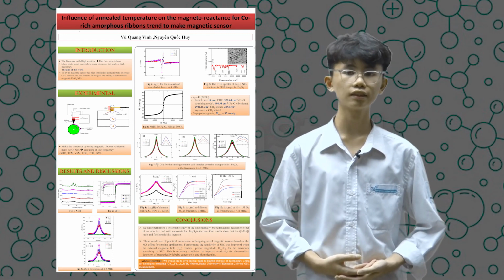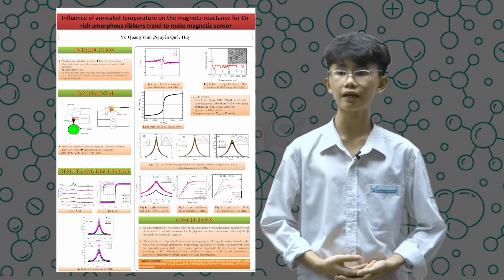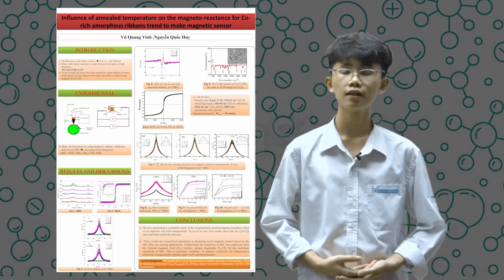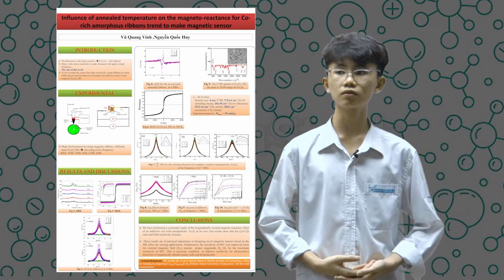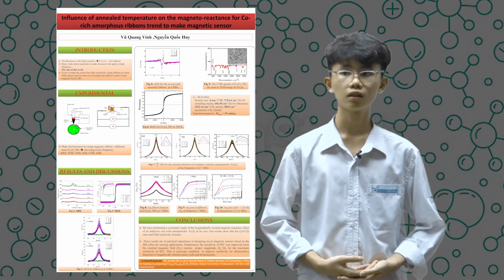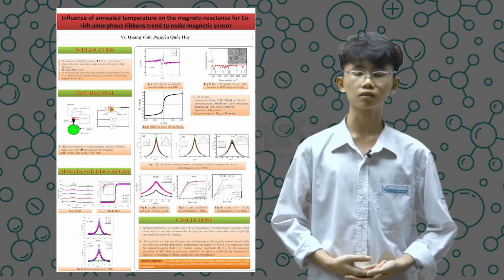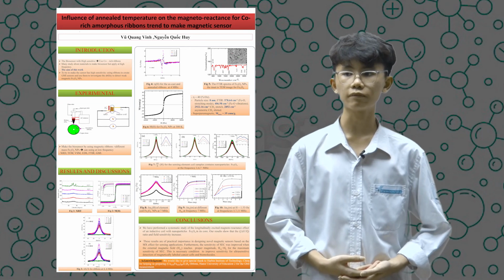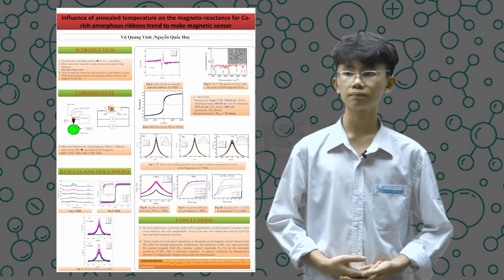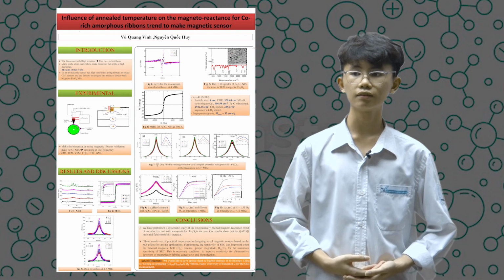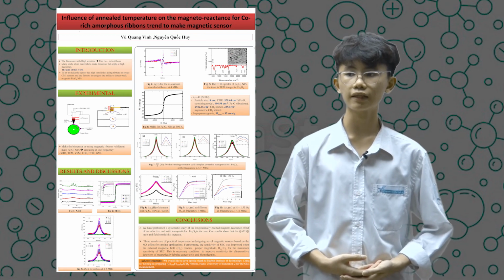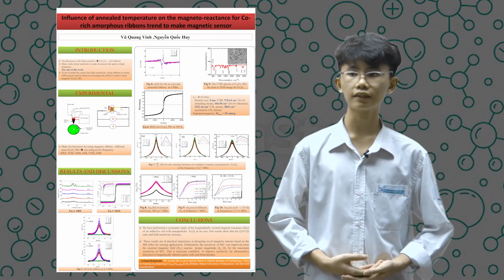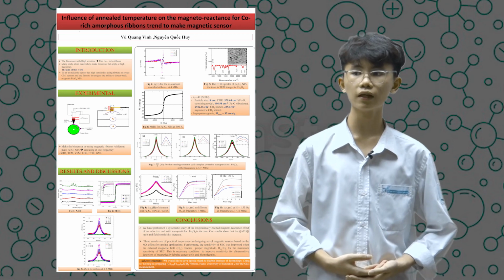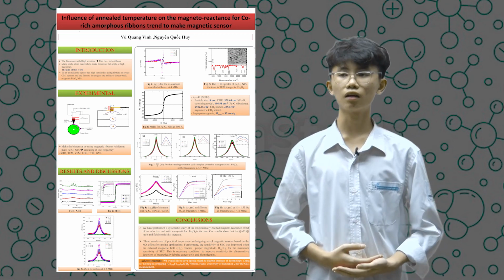Clearly, the concentration of 1.92 mg sets an upper limit of the sensor detection of 8 to 12 nanometer iron oxide nanoparticles. Conclusion: we have performed a systematic study of the longitudinally excited magneto-reactance effect of an inductive coil with iron oxide nanoparticles in its core.